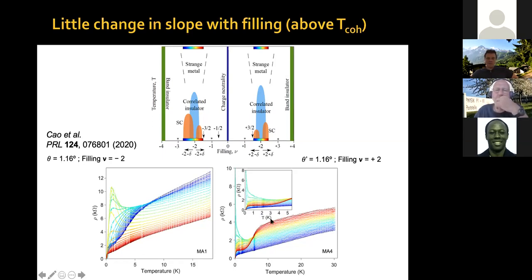In particular, the offset resistivity at zero temperature is not the highest at the correlated insulator state. I'm not sure if it's easy to see, but this green trace, this green region, is the middle of the correlated insulator state. You can see at low temperature, this diverges. It's a little bit hard to see in the contrast, but in the zoom, it diverges. But the green trace does not exhibit the largest offset, residual resistivity, right? Nearby regions, this red curve, shows a larger offset resistivity. We don't know why, but I can tell you that we have seen very often, also in this case, that the largest TC seems to go with the largest residual resistivity. Having large residual resistivity is good for high TC somehow. That's something that we've noticed in many samples. We don't have a detailed understanding of why.